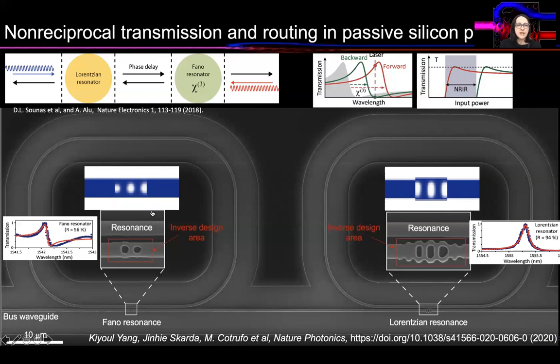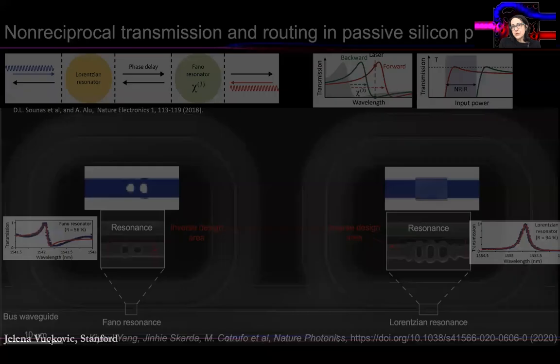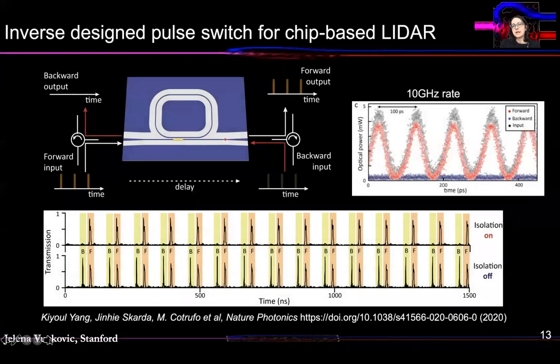Transmission characteristics is basically shown here as a Fano resonator, and here as a Lorentzian resonator. You here see the evolution of the inverse design. And once you reach the final design of the coupling elements, they look like something shown here in a very small footprint. And then you implement those elements, measure transmission, and it matches theoretical behavior given by the red curve. So with this, you expect to observe non-reciprocal transmission, and indeed that is what we achieve if you are in the range of powers where you expect non-reciprocal behavior.